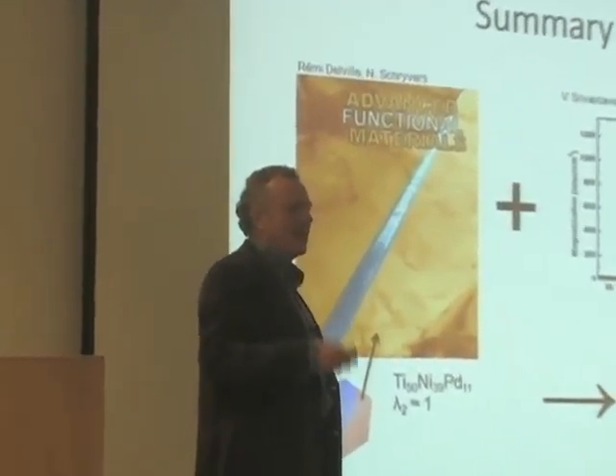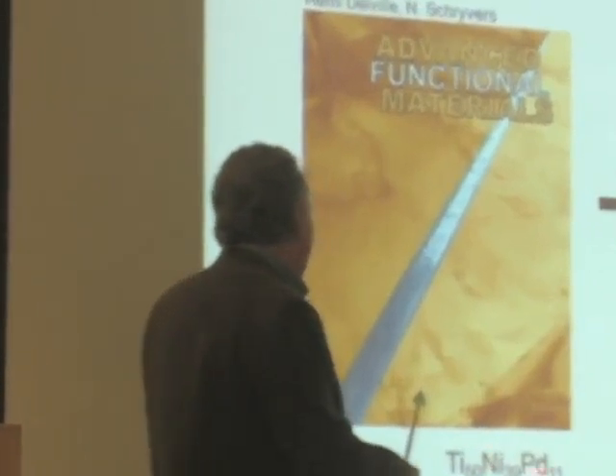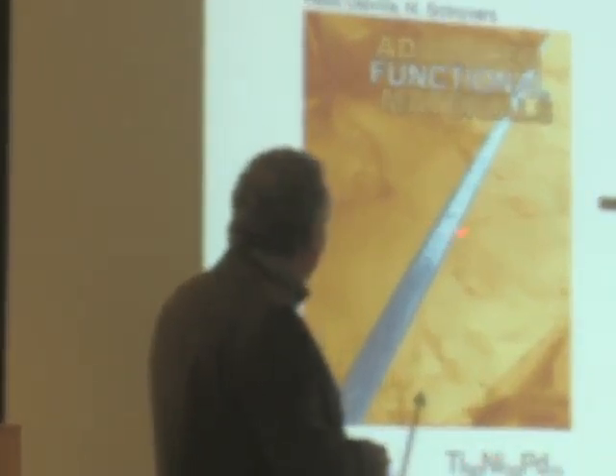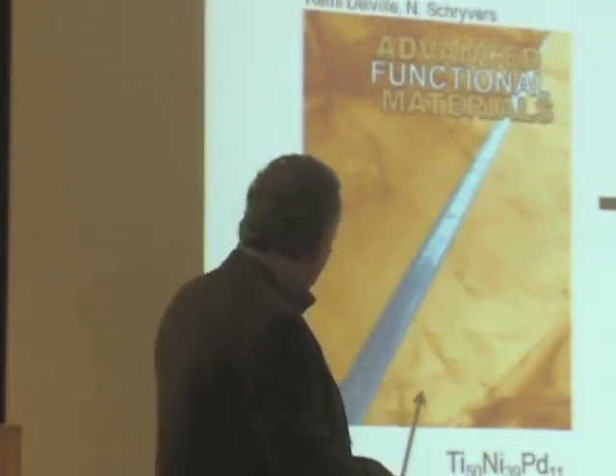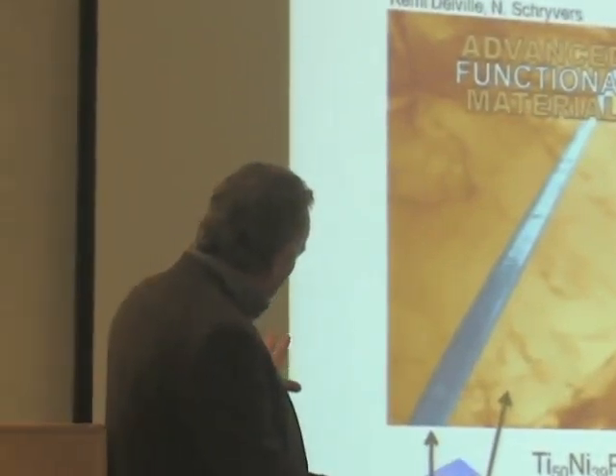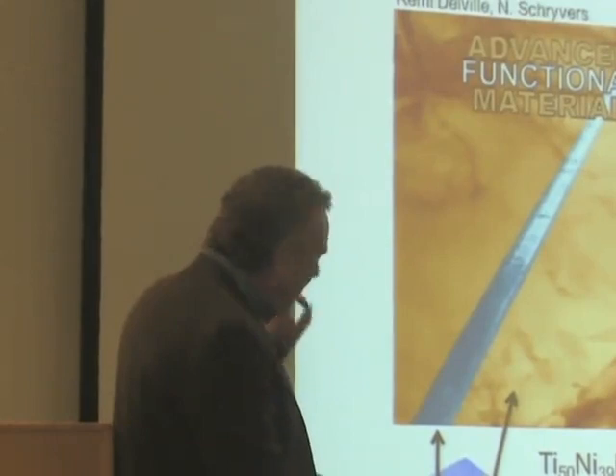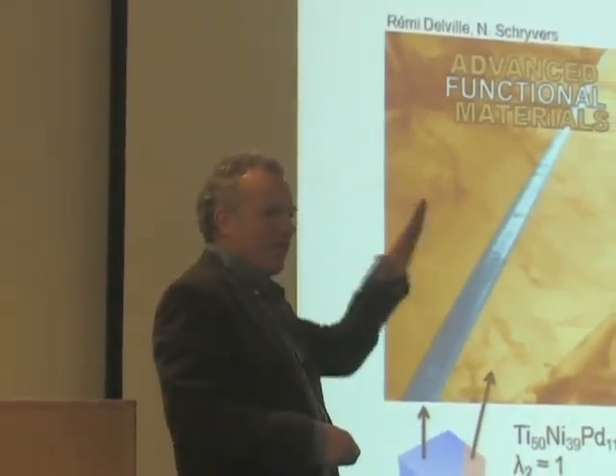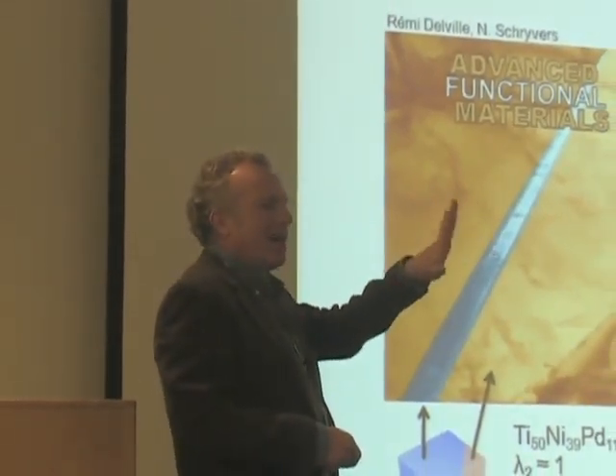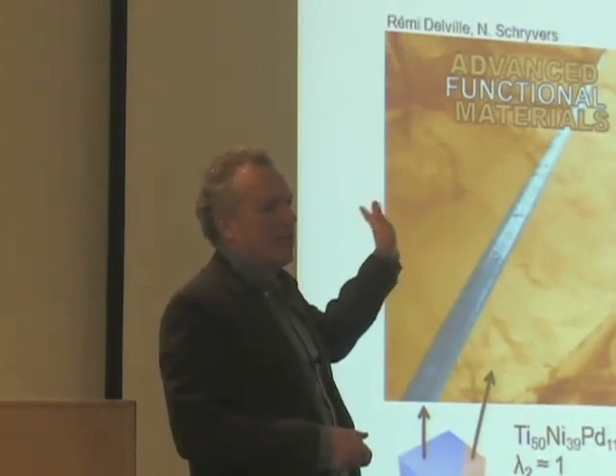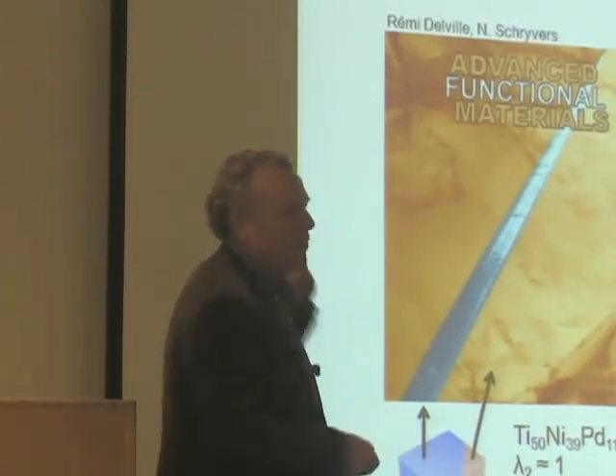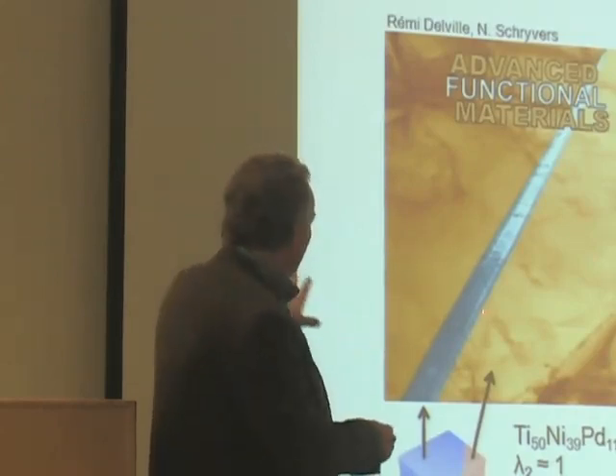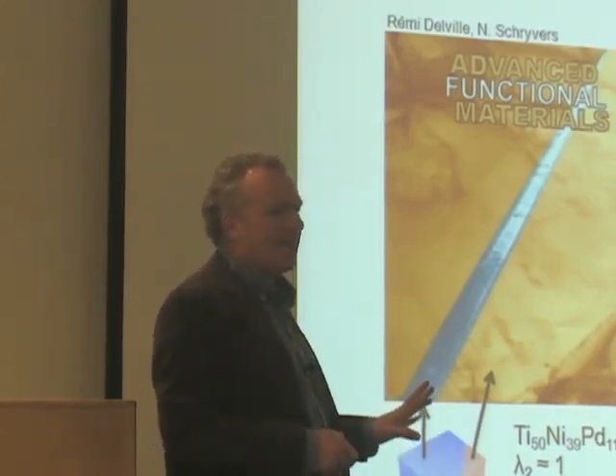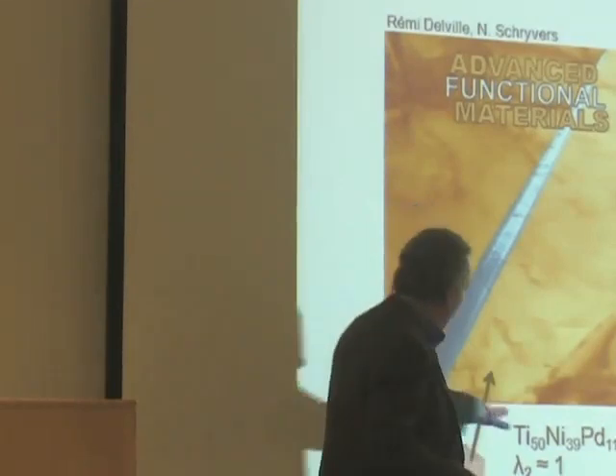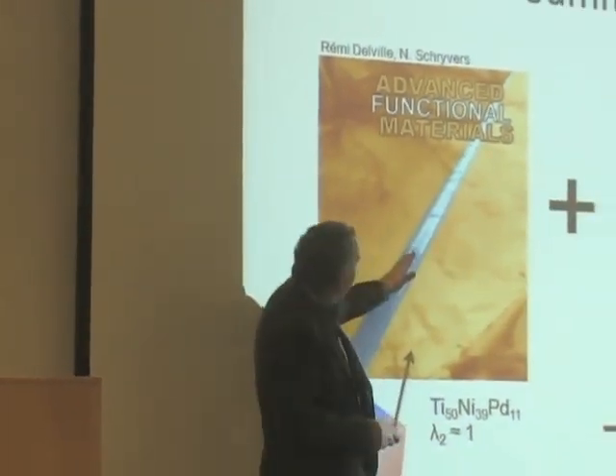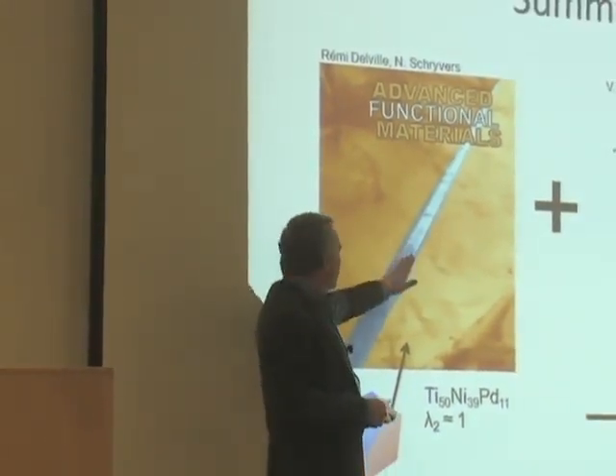And I think, if that's the case, there's not a single interface here. There are several different interfaces nearby that are nearly compatible interfaces for this. And I think you're seeing two of those interfaces. So that's the explanation here. I would say this is slightly stressed. The real lambda 2 equals 1 alloy, if I took 9.25, would probably lie in the middle of this. And the fact it's perturbed is from the fact that this is not exactly satisfying lambda 2 equals 1.